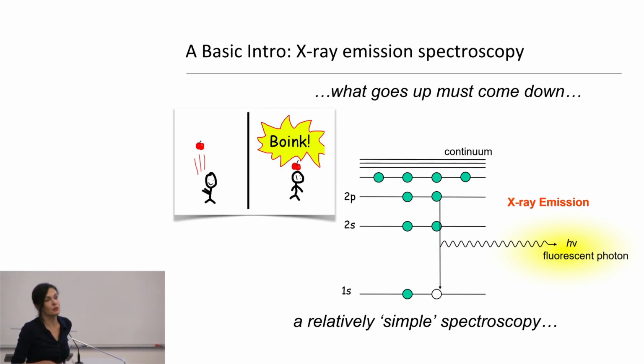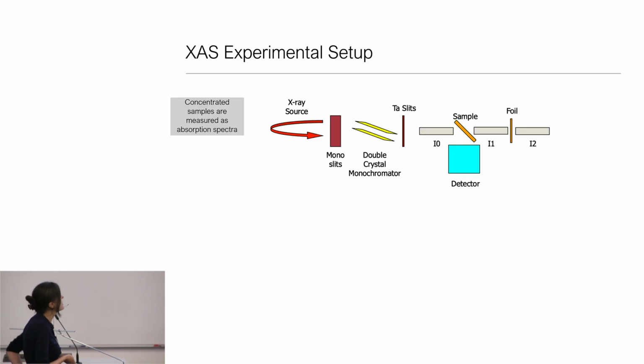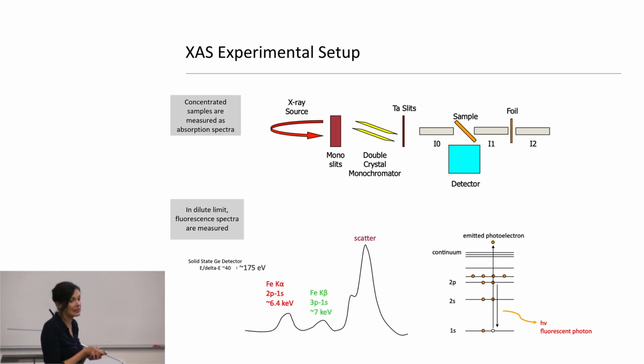So I already alluded to the fact that in X-ray absorption, we rarely do a true absorption experiment. Most of the time, what we're really measuring is the total fluorescence or partial fluorescence yield. So we're looking at what happens when the system relaxes back down and a fluorescent photon is produced. In a standard experiment, this is basically the same diagram that I showed you before. We generally have our sample rotated 45 degrees, and we're using a solid state detector to measure the fluorescence. Now, what is that solid state detector actually seeing? It's basically measuring the energy of deposited photons, but at relatively low resolution. And this is hand-drawn, so I apologize if it doesn't look real.